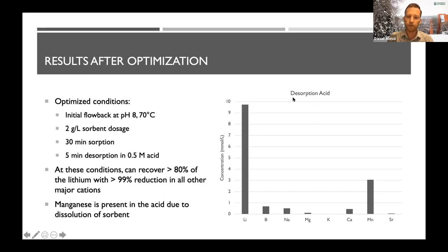And this is the chemistry of the desorption acid, the concentrate that we had. You can see lots of lithium. Yes, some of the impurities were carried along: boron, sodium, magnesium, calcium, potassium, a little bit of strontium. But keep in mind, sodium was originally present at thousands of times more than lithium, so this is super selective. The selectivity factor is many thousands. We still want to get rid of this because we're not going to produce 99% grade battery salts from this. But the issue here is manganese. This comes not from the brine, but from, remember, the sorbent itself. The DLE material is made from manganese.